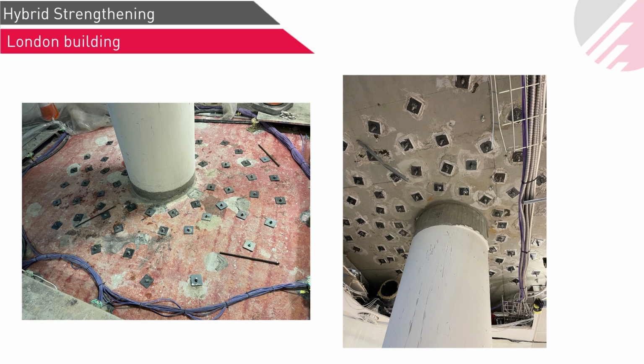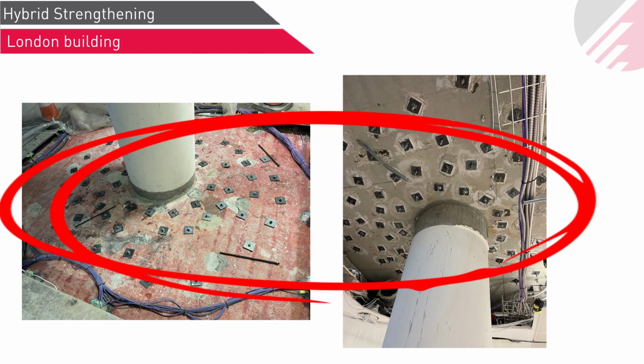But as well, when they were assessing the structure, investigation was done, and they also found that the punching shear reinforcement in the slab was not adequate as per the current codes and the design requirements. So they had to do punching shear strengthening. So again, both types of strengthening techniques were used. Traditional method using these shear studs, which was also done by us.